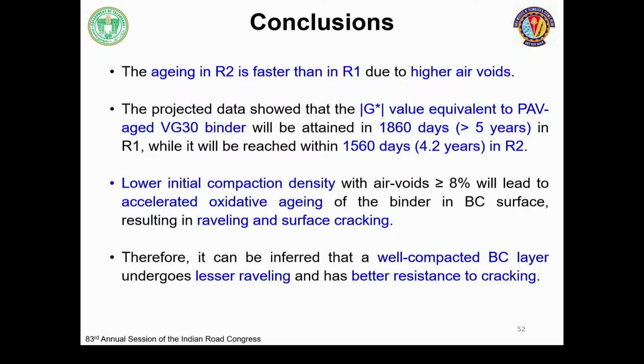Also, the projected data showed that the G star value equivalent to PAV-aged VG30 binder would be reached after around 1860 days. But for R2, it was around 4 years. And our prediction came out to be true because they have milled and resurfaced or milled and patched at a few locations where there was cracking. It is not a bad construction, but some precautions should have been taken.